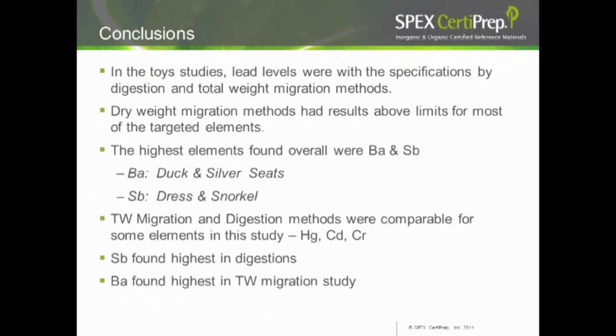In conclusion, the lead levels that we expected to find very high in these toys were all within specifications despite whatever method we used, the digestion of the total weight. Now, if we had been able to isolate more of the paint samples, or we had a bigger sample batch to collect a larger sample size of the different paints, that might have changed. But as the toys were ground homogeneously in some cases, or we did try to isolate a small amount, that just wasn't enough in order for us to find the lead in our extract or our digest. It was not possible necessarily to see the lead in those paints.